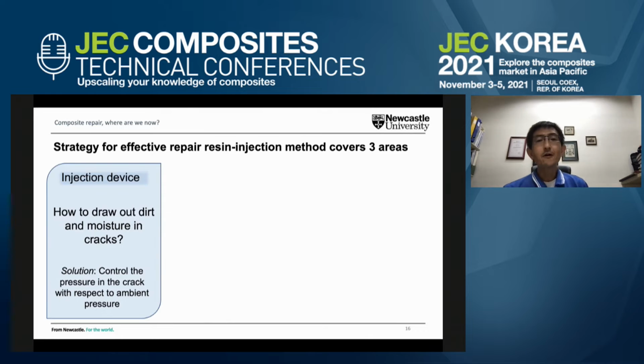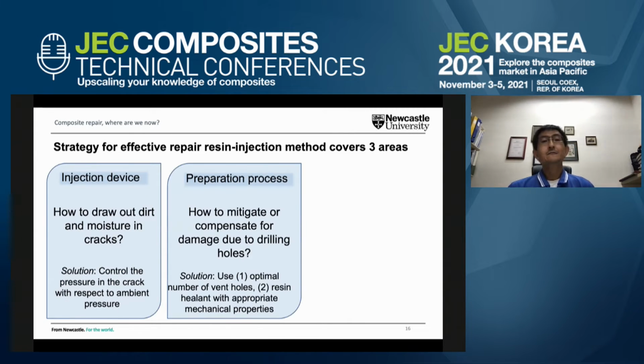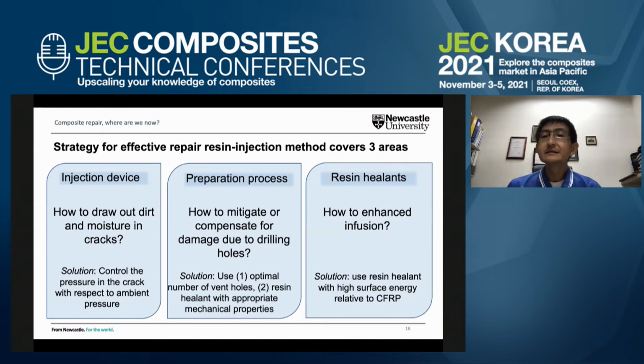What we understand from the resin injection method, in order to carry out an effective repair, is that this covers three areas. We have to deal with the injection device, we have to deal with the preparation process, and the resin healants for the repair. And all these would involve issues like how to draw out the dirt and moisture from the cracks effectively, how to mitigate or compensate for damage due to holes drilled, and how to enhance the resin infusion into the crack.